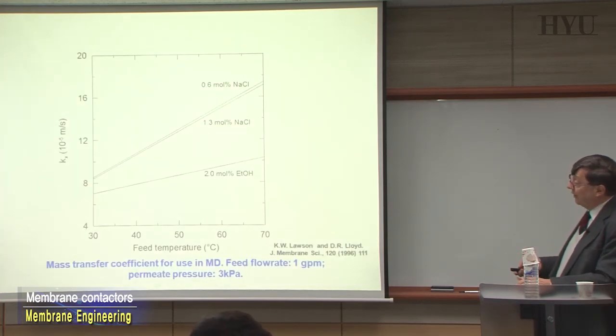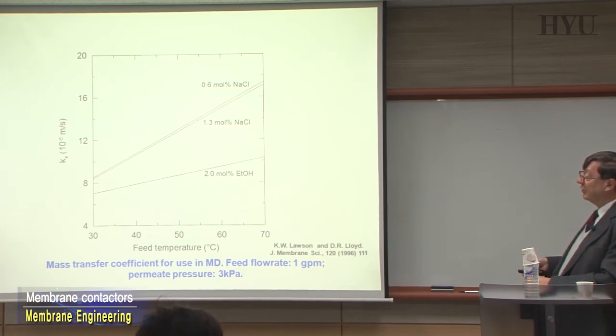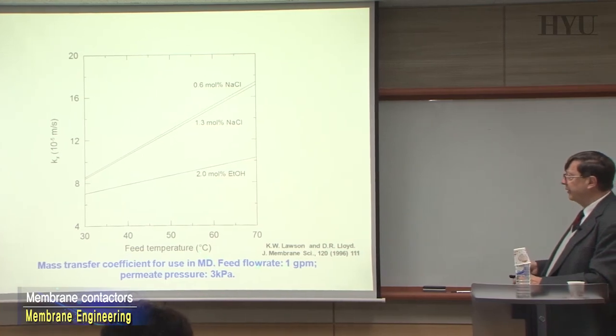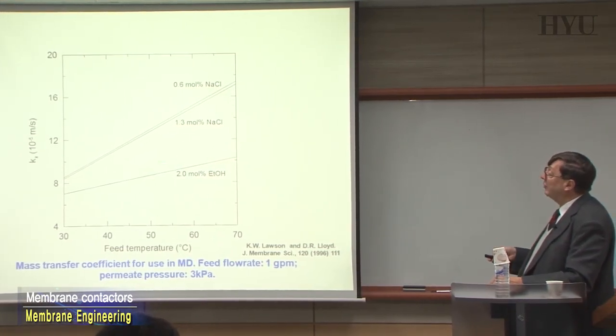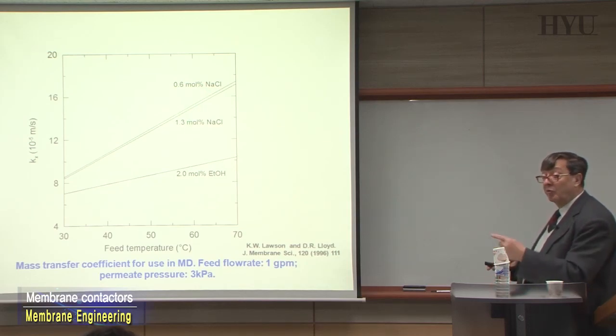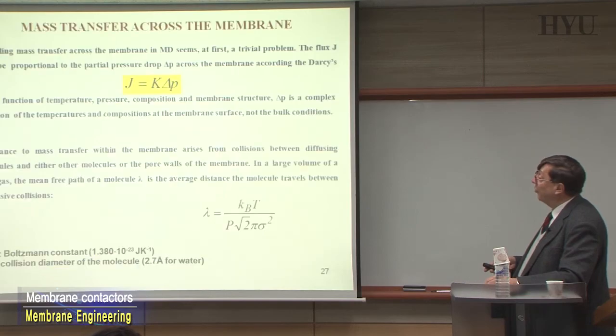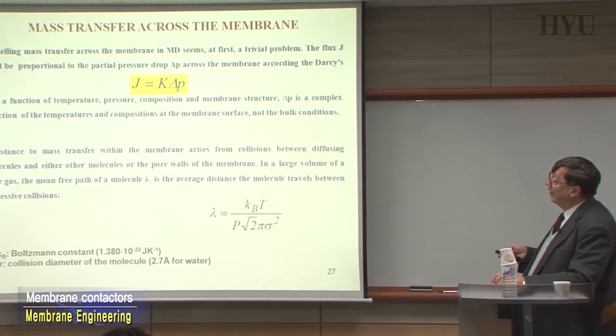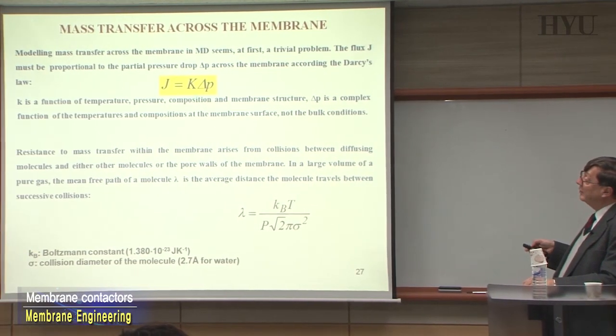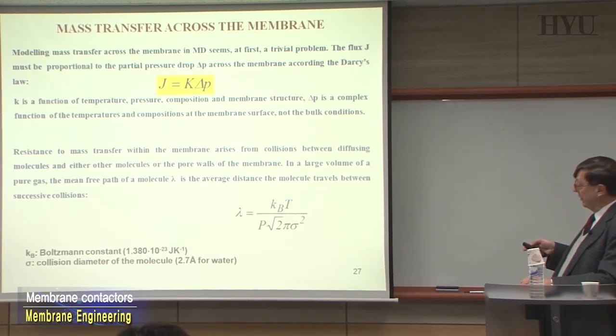And here is the effect that you can have. For example, the mass transfer is a function of the feed temperature, and that is a typical expression. Again, you can find this linear relationship as a function of the concentration of the species that you have, going from 0.6 molar to 1.3 molar. There's not a big difference, confirming what we were saying before. Across your membranes, that is the typical relationship that we have to consider.